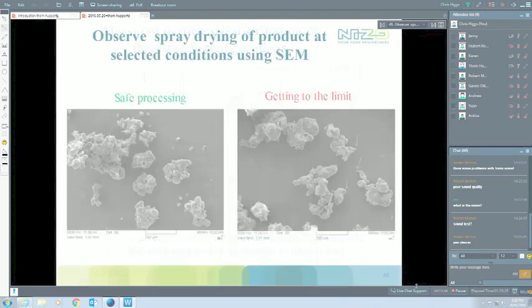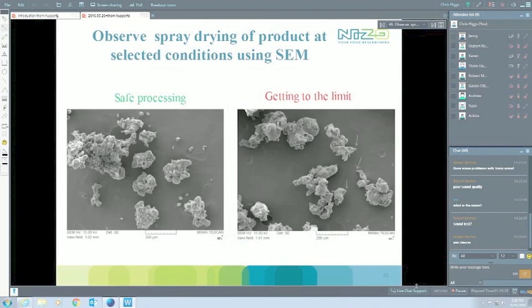Of course, the next step was to start making milk powders with those combinations and look at whether it works. Can you push it that far? And the good thing was, yes. If you push it a bit too far, you can start seeing issues. Under normal conditions, what we nicely see if we put it under a scanning electron microscope is some nice agglomerated powders that will dissolve well, pretty much spherical particles that are agglomerated.